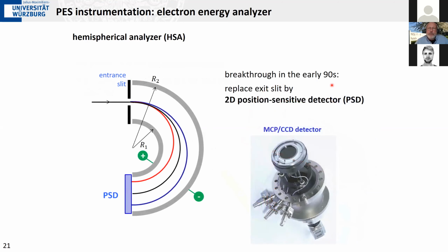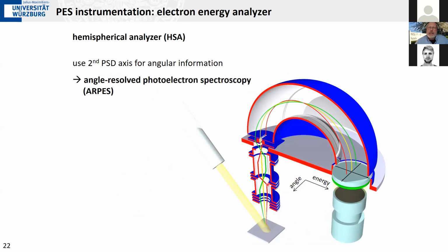Now, the energy, as I said, is encoded in this position here, in this linear deviation of the different paths that the electrons travel in our analyzer. But as I have a two-dimensional detector, I can also use the other direction, and that can be used to measure the angle with which the electrons have originally escaped from the solid. Here you see three beams, green, yellow, and red, that have different escape angles. They are imaged onto the entrance slit, come into the analyzer, and now let's assume that they all have the same kinetic energy to hit the middle line of our detector. So they will be recorded as having this particular energy. If they had a higher energy, they would have been detected further out here, and if they had a lower energy, they would have been detected here.